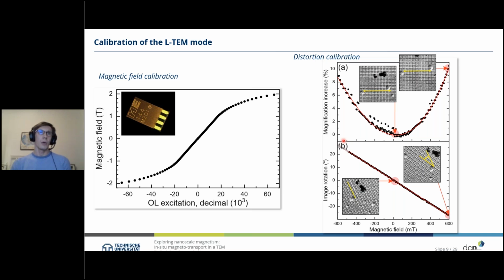First of all, we want to know how large the magnetic field is which we generate at the area of our sample. That is measured here using a standard commercially available Hall sensor, shown in the image in the inset on the top. We calibrated that Hall sensor in a cryostat. These Hall sensors are linear in response to the applied magnetic field, which is quite nice, but you still need to know the calibration, of course.